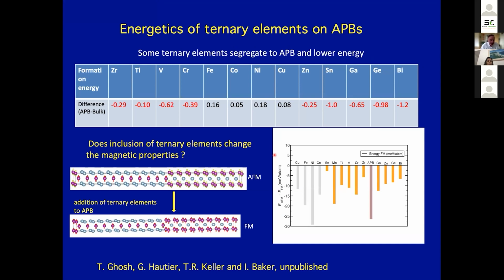So there's been a number of pieces of work on adding ternary elements to manganese aluminum, just on a throw something in, let's see what happens basis. We decided to do some first principles calculations on this and looked at putting different elements actually on the antiphase boundary and what that would do to the energy of the antiphase boundary. And what we found was that these elements that are shown here in red actually decrease the energy of the boundary. So you'd expect those elements to actually segregate to the antiphase boundaries in the material.